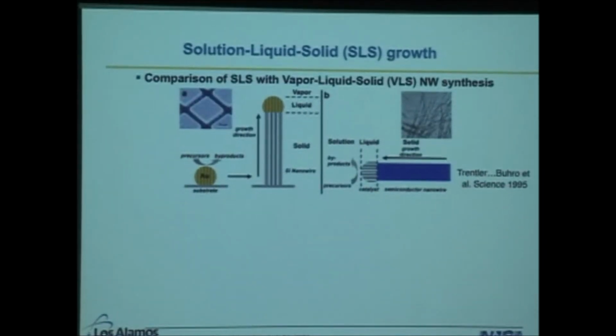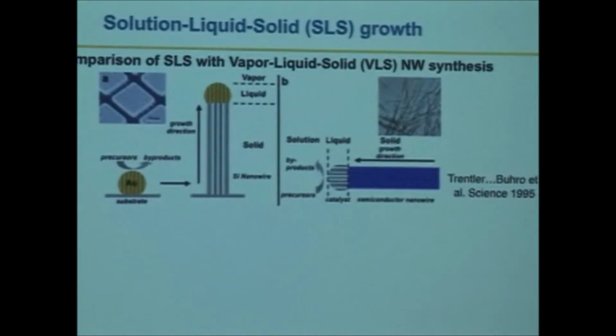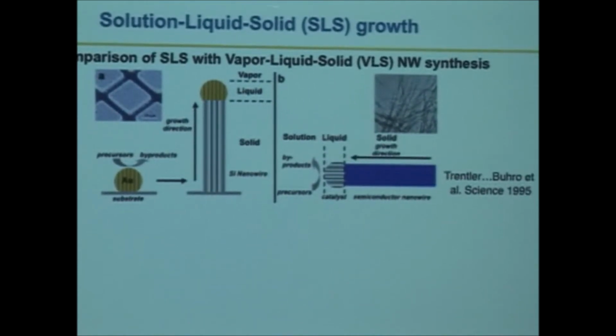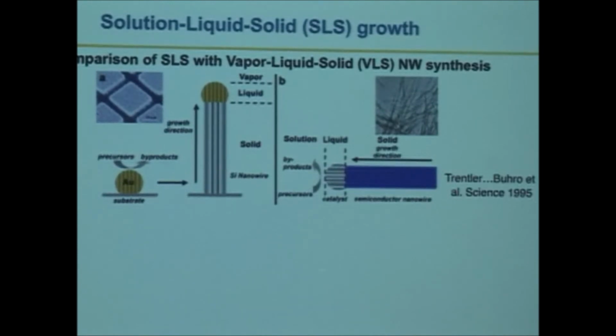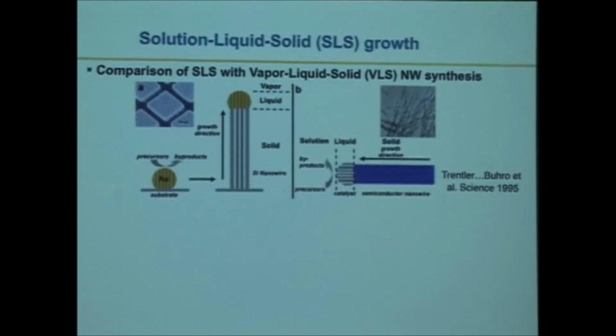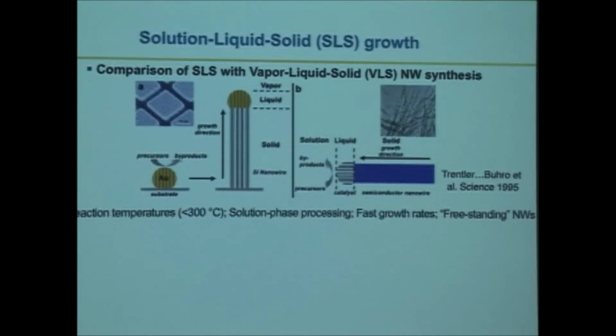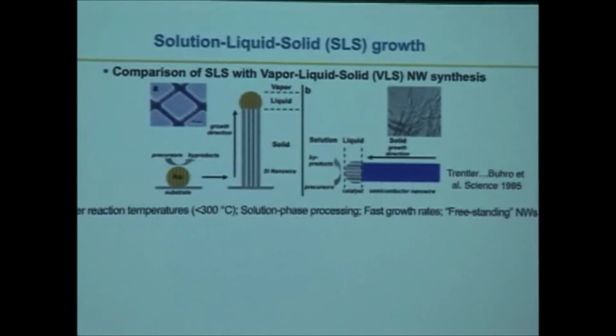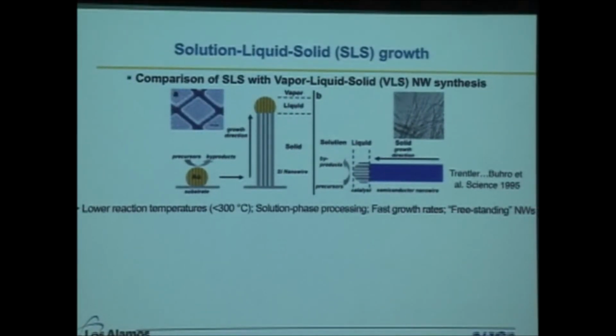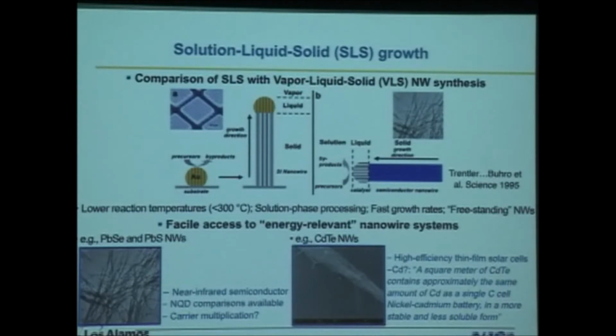Bill Buhro was here not that long ago, and he is the father of solution-liquid-solid growth, and in this work I largely follow that methodology. It's similar to vapor-liquid-solid growth in terms of mechanism. In both cases, you have a molten metal flux into which you incorporate precursor compounds, and upon supersaturation, your semiconductor material nucleates and then begins to grow. We do the same thing in SLS, except that things are happening in solution, typically at lower temperature, and we also get significantly faster growth rates, so many microns of wire are popping out in seconds, and the wires are freestanding. We use this in our lab in general to grow a number of systems. It gives you great flexibility, just like the quantum dot approach to synthesis.